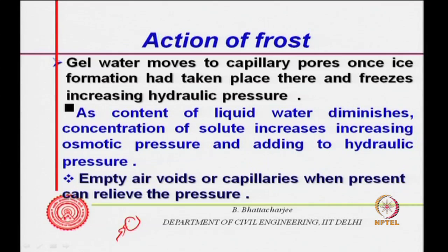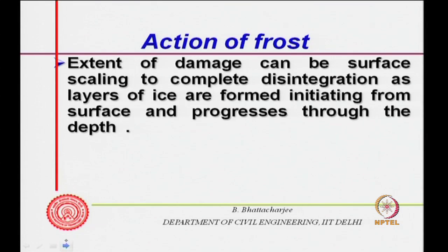So, empty air voids, if present in the system, will cause release of the pressure, and thereby the disruption or deterioration of concrete is controlled. The extent of damage can range from surface scaling to complete disintegration, as layers of ice are formed initiating from the surface and progress through the depth. So, essentially it starts from the surface and penetrates inside, with surface scaling and sometimes complete disintegration of the concrete from the surface and so on and so forth.